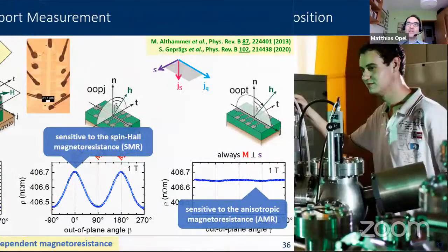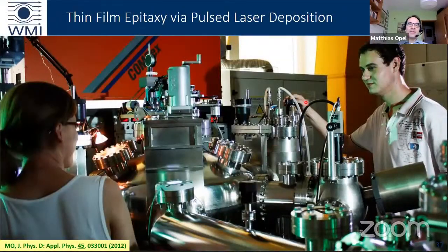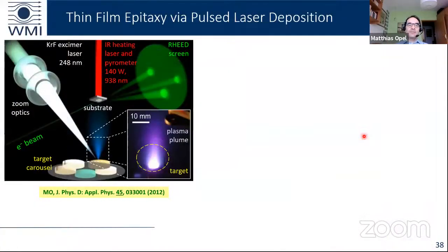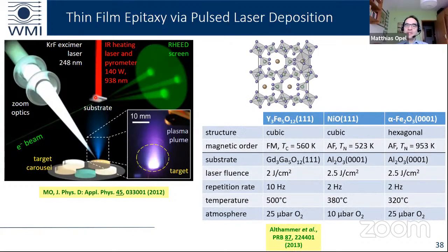We fabricate our samples using pulsed laser deposition in our labs. So this is a photograph of our lab. The principle of pulsed laser deposition is well known here. We use an ultraviolet laser and hit the polycrystalline target of the material we want to deposit. There we create a plasma and we place a substrate in the plasma, and then we deposit the plasma on the bottom of this substrate.